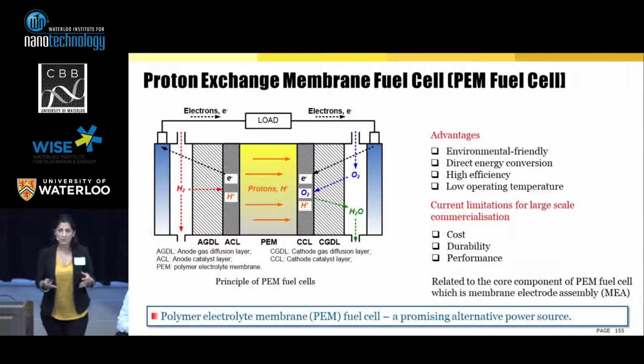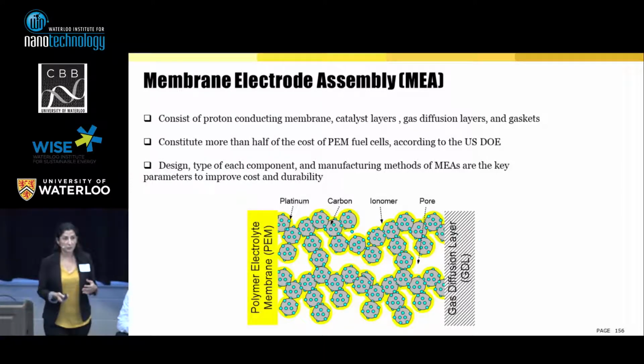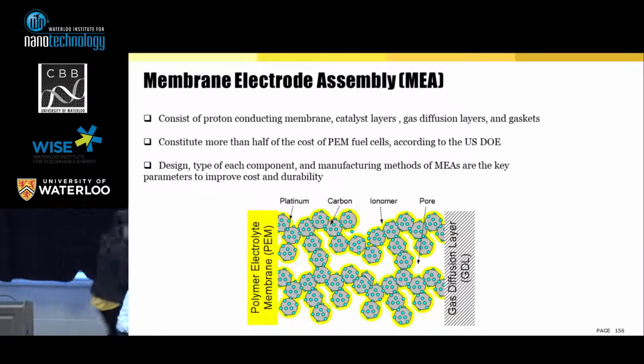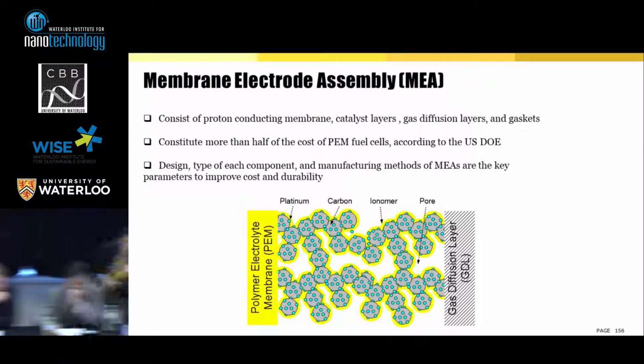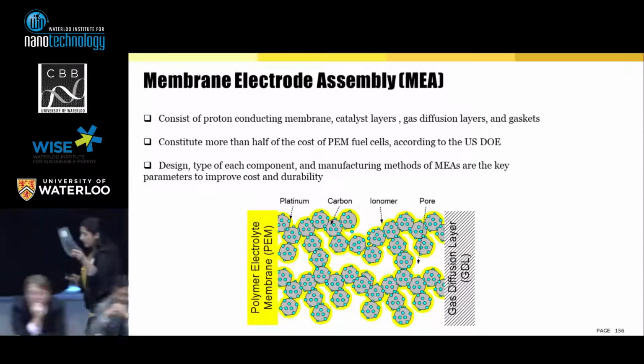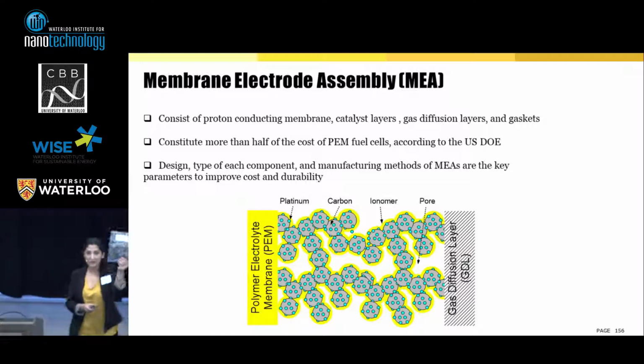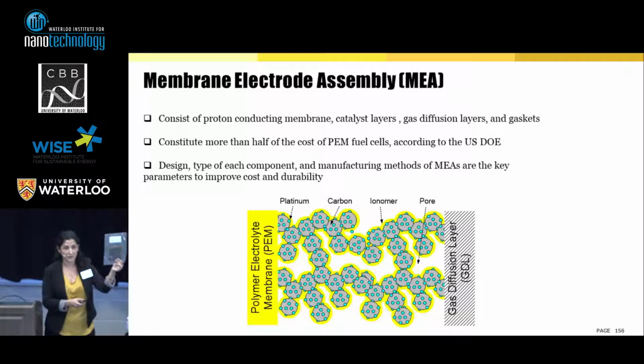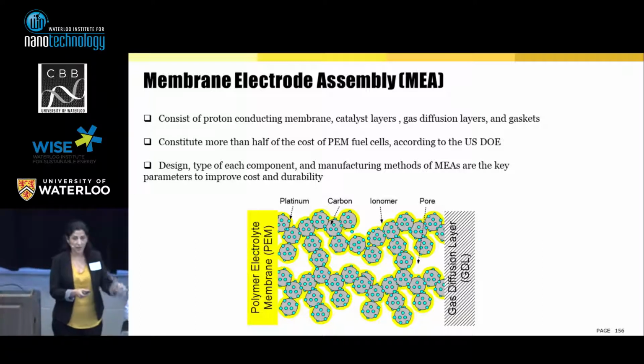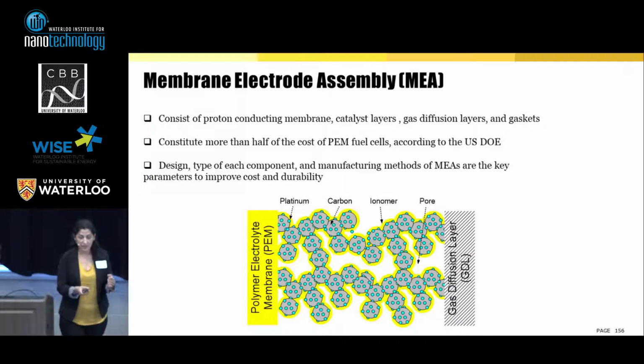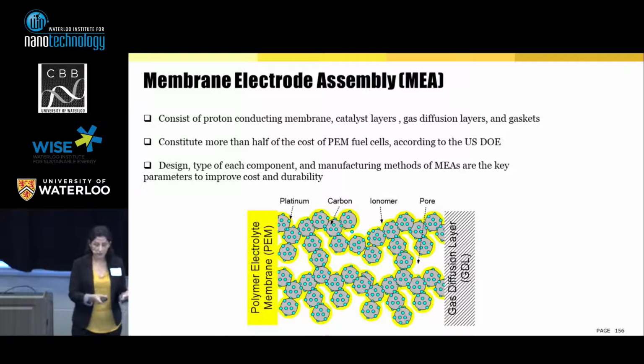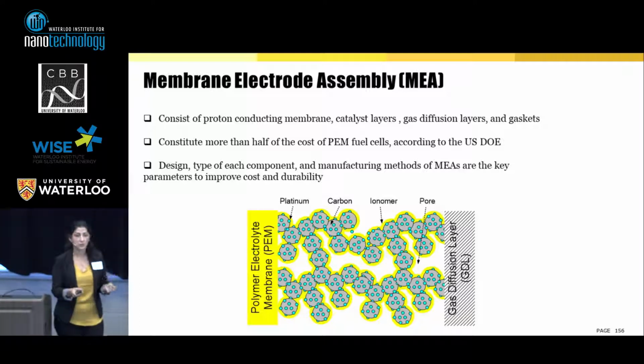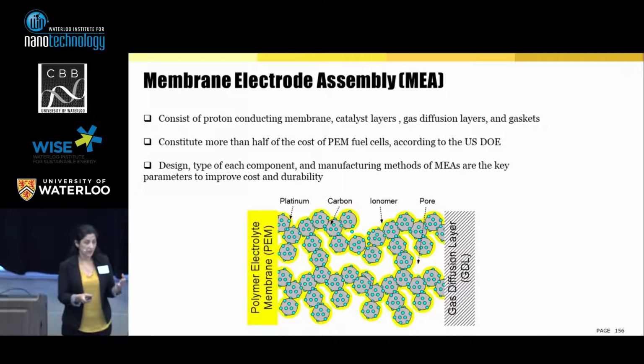All these 3 issues are interconnected and related to the membrane electrode assembly. But what is the membrane electrode assembly? Actually, I brought one to show you, and if you're interested, later you can come and see it over there. All the things in a fuel cell happen in these thin layers, less than 500 micron, okay? What we have here is a membrane, catalyst layer, and gas diffusion layer. In the catalyst layer, we have a catalyst, of course, and the best one so far is platinum. We have carbon as a support, and the ionomer, and each of those plays an important role in the performance and durability of the MEA.